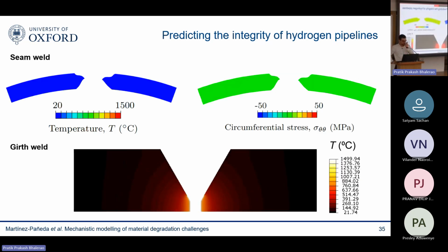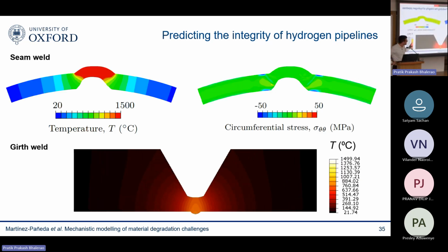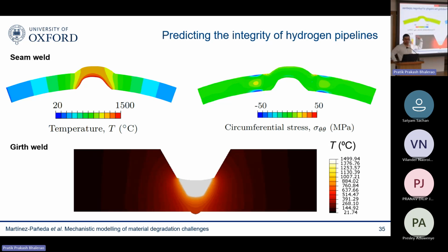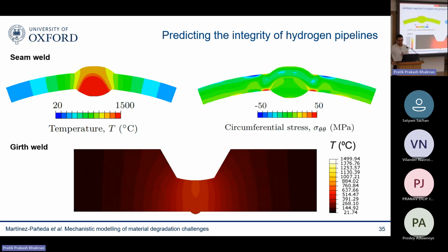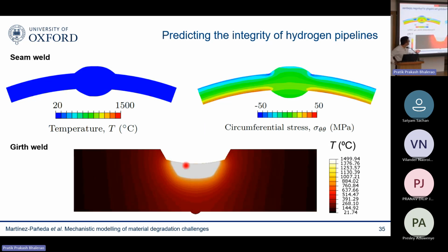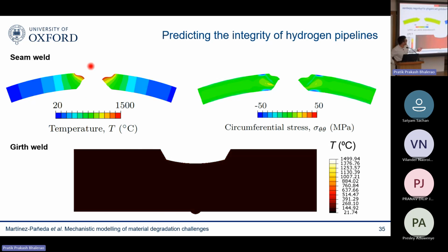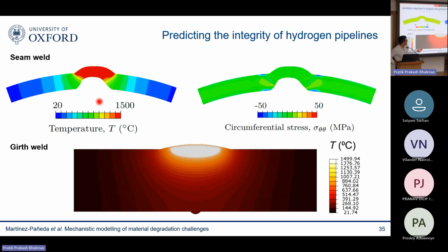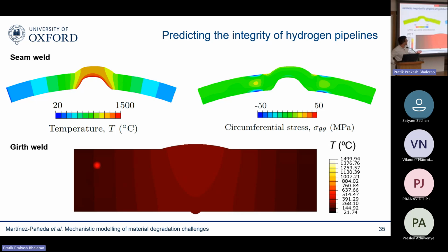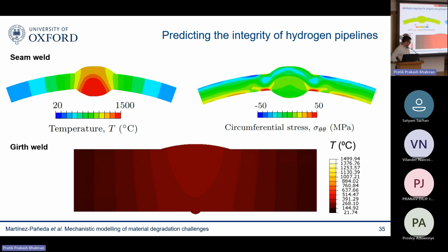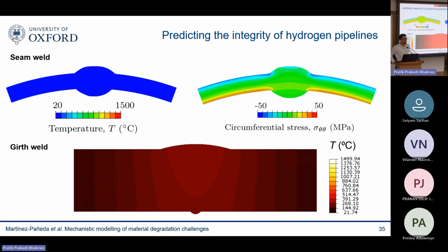And then the next step was to simulate the welding. And again, it's not an area that we have pioneered. We just took this welding process modeling off the shelf. So you can see here the top seam weld. This is a 2-pass seam weld. So you put the 2 passes. You see how temperature and residual stresses change within the material. This is a girth weld where you have multiple passes.